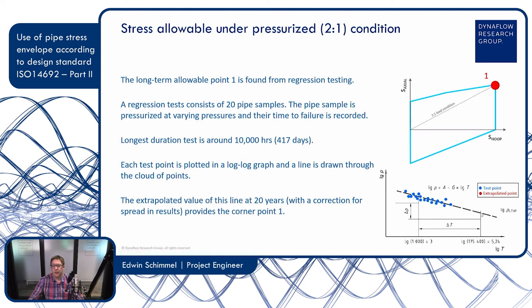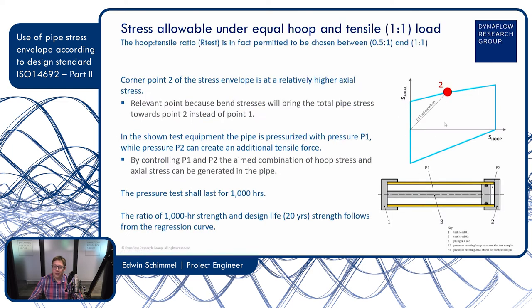So the ratio is smaller than 1. For 20 years, we have a lower strength than for 1,000 hours. And this ratio for this test under a 2:1 load condition is also applied for this 1:1 load condition. It's, of course, not 100% proven that the same regression ratio applies to this different load condition, but yeah, it's reasonable to assume it is at least close to it. So this we will use. And this is what the design standard ISO 14692 uses. So that's how we get the second point.